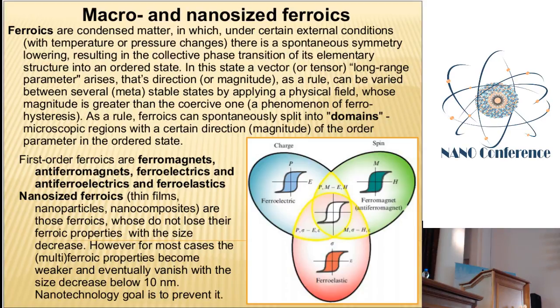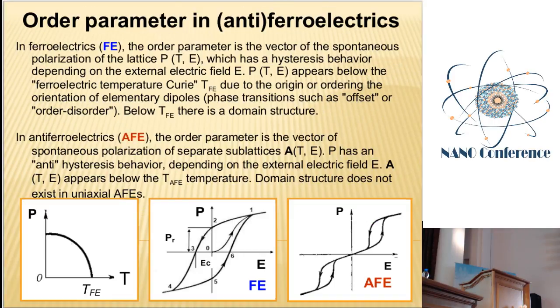And the problem here is not only that the property can disappear, but also that the property can change. For instance, most of us know that there are hysteresis and antihysteresis. The difference between them is shown at the bottom of this slide. The hysteresis is a single loop, and the order parameter is the ferroelectric polarization, the elementary dipole moment of the ferroelectrics, which has a critical electric field, the so-called coercive field, at which it changes its direction.